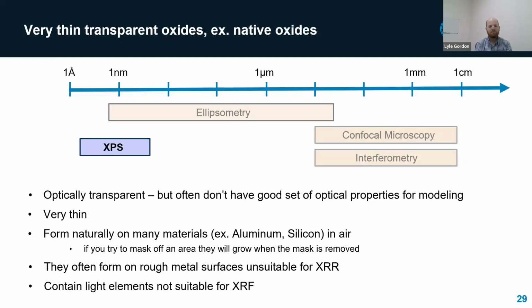So this is a really common application, for example, on semiconductor wafers like silicon, as well as metals like aluminum. They form a very thin so-called native oxide when exposed to air. And this is on the order of maybe a few angstroms to a couple nanometers thick. And while it is typically optically transparent, you can see through it on a piece of aluminum or silicon, we don't often have a good set of optical properties for modeling this, and it's very thin. And you might think that you could use the step height approach, just remove the oxide, but unfortunately, in most situations where we're handling these samples in air, the native oxide will just grow back before you can measure it. And so that will be a difficult approach.